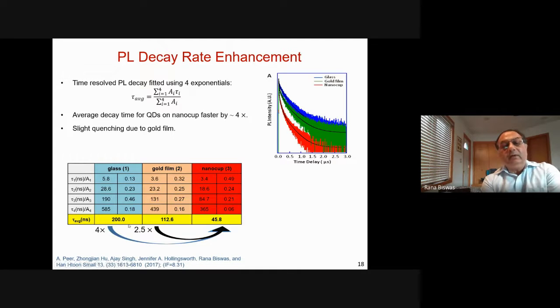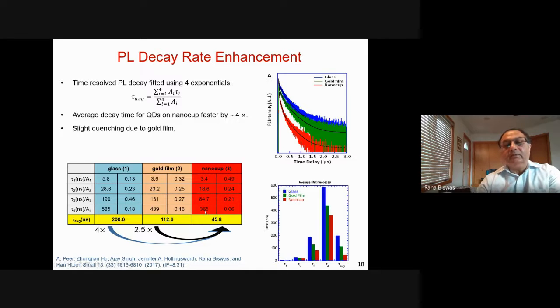So the average decay time for quantum dots is faster by a factor of more than 4 when you compare nanocups with the glass. And there's a slight quenching for the gold film as well. So it's a very marked effect, and you can see that in all of these exponentials. The nanocup is always the shorter time, and it's in fact quite a bit shorter.